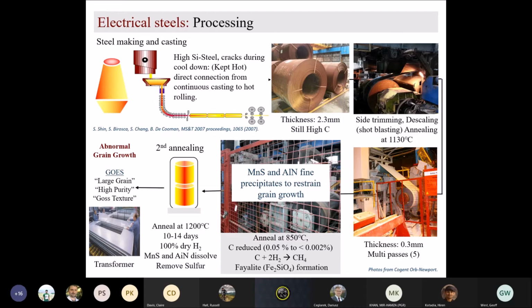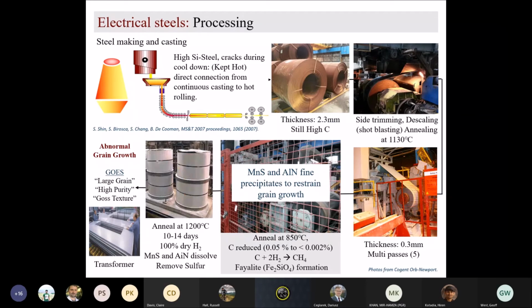Because we don't want abnormal grain growth to happen in the primary annealing. And then the secondary annealing will start, where we anneal it at 1200 degrees Celsius. Still, we are in alpha phase. There is no austenite because of the silicon and aluminium effect. And we leave it at 1200 for nearly 2 weeks in dry hydrogen.